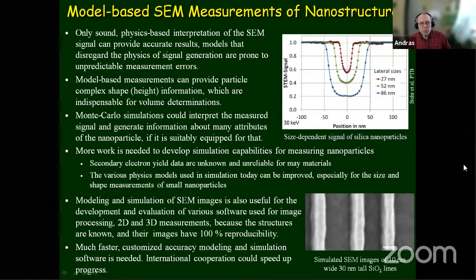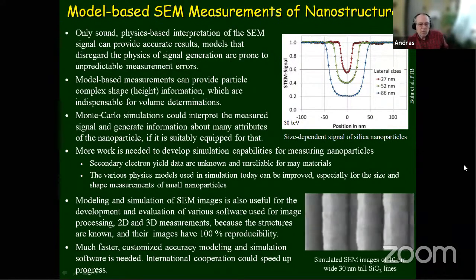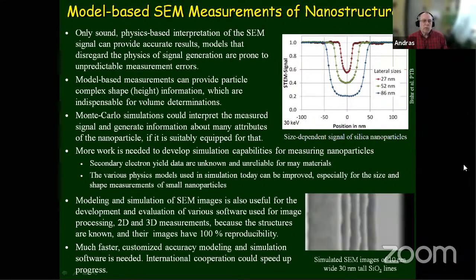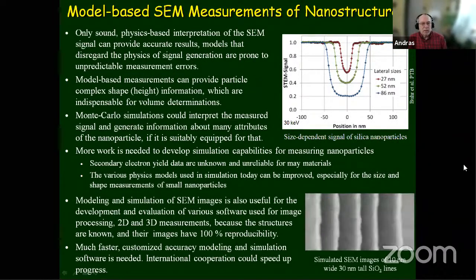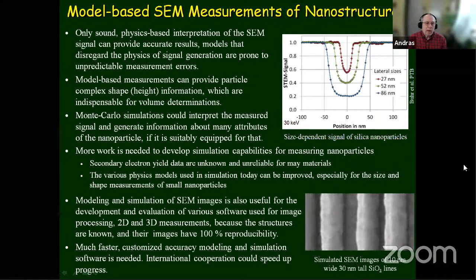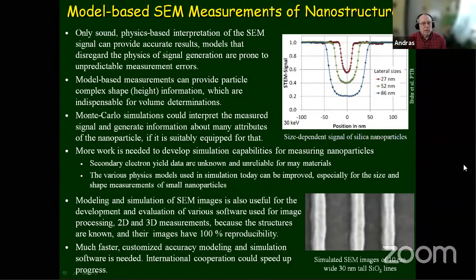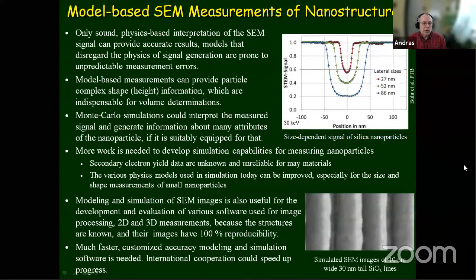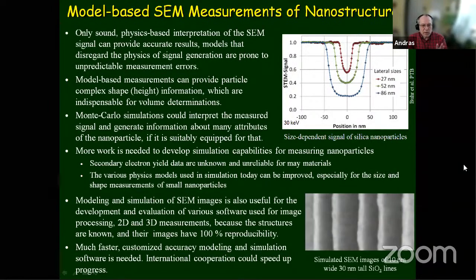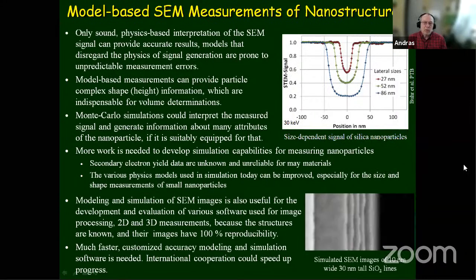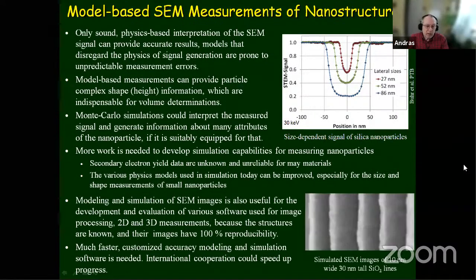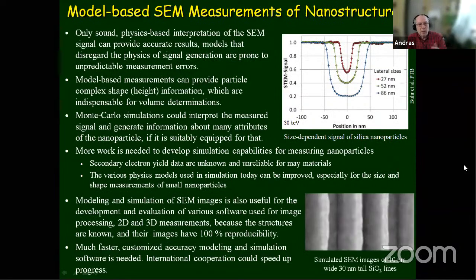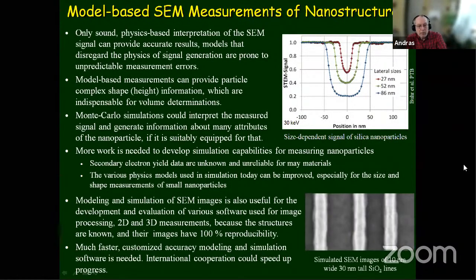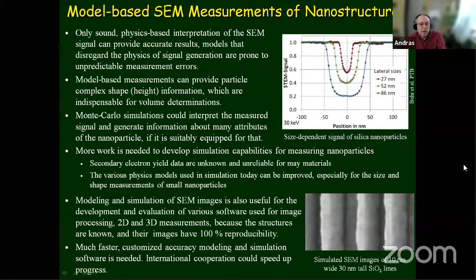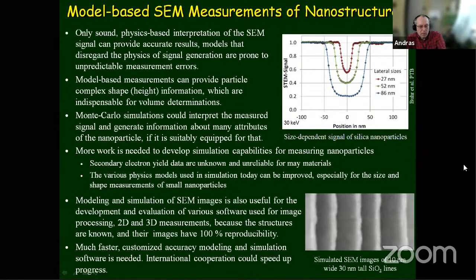And obviously these samples are not really spheres, but this is a step forward for sure. The lower image, which is moving, is a simulated SEM image of 10 nanometer wide, 30 nanometer tall structures. These are important for integrated circuit measurements. And these are very useful to check different software that can evaluate 2D and 3D properties. There's some surface roughness and height variation and so on. So this is a sample, and a series of SEM images played in a moving file that have never ever seen an electron beam, only model. Slide, please, and simulation.